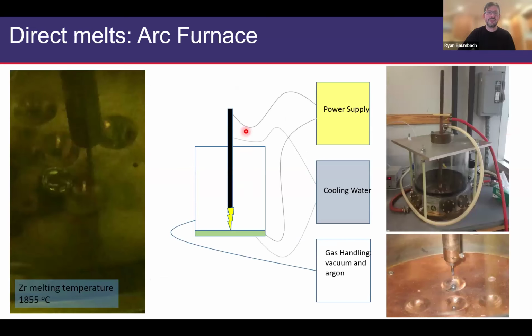A very useful method that you're going to see during the practicals is the arc furnace method. That's shown schematically here, and in reality, on the right-hand side, where you have a bell jar, you can introduce an inert gas like argon, and then into this space, you'll insert what we call a stinger that's attached to a welding power supply. And then using this, you'll be able to discharge an electrical arc through your sample down into a hearth, which is usually something like a water-cooled copper plate. And that's shown in the lower right hand here. Okay, so this is the general idea of how an arc furnace works.